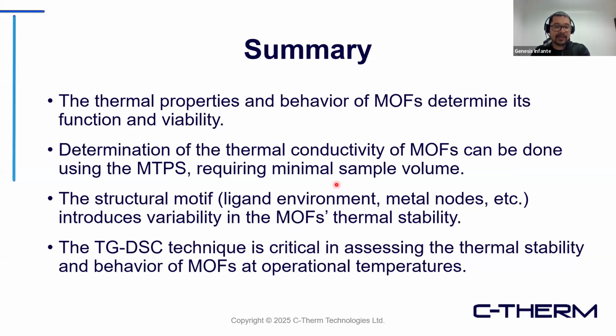Here's a quick summary, just going over the different points during the talk. You can see that thermal properties and behavior of the MOFs really determine their function in general. The determination of the thermal conductivity of the MOFs, we can do that using the MTPS, requiring very minimal sample volume, and again non-destructive and in a very rapid testing time. Structure motifs such as ligands, metal nodes, even the environmental conditions can really introduce a lot of variability in how the MOF's thermal stability and behavior can occur. And it's kind of a double-edged sword because you can fine-tune it, but at the same time, you'll never really know what happens until you do your testing and make sure that it's robust against the conditions that you want to avoid or target.